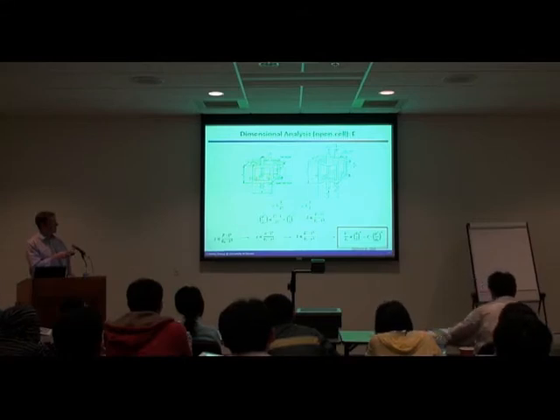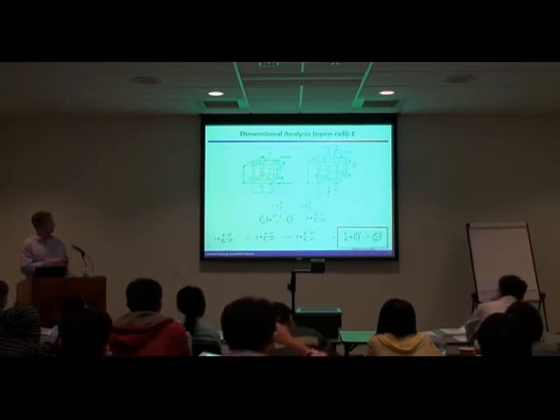So when you think about using a dimensional argument, you have an individual unit cell that has given associated lengths to the fibers and associated thickness of each fiber. So if you start thinking about trying to describe the relationship between the applied force on this unit cell and the stress in the unit cell, which scales as a length squared, which would be sort of the top surface of this biomaterial, and there's also a relationship between deformation and strain, again by length. So then you can start describing what the deformation of one of these fibers might be under load, and there is a column buckling equation you can use.